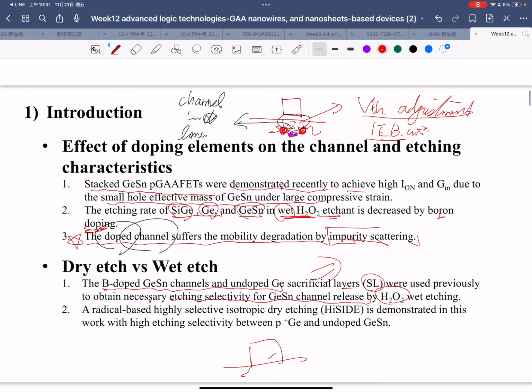So actually they have another paper. They use boron-doped germanium, and they use H2O2 to remove the germanium, and then keep their germanium. They use boron doping, but the trade-off is, I think, etching selectivity and mobility. So dry etching is very important.